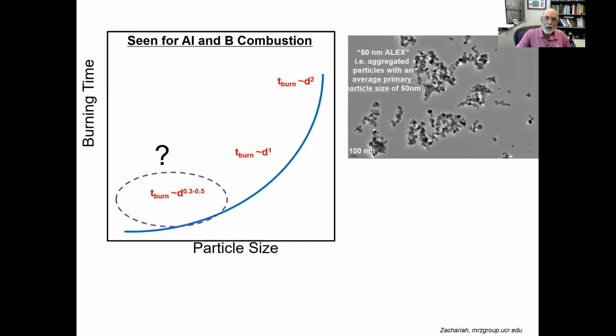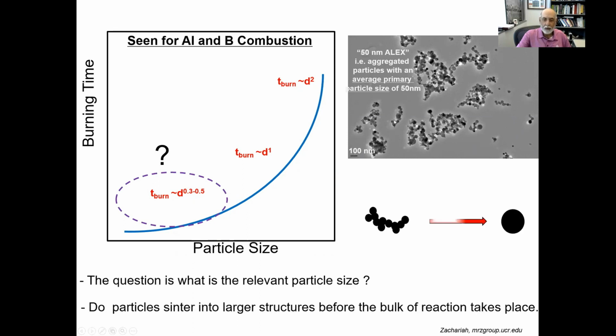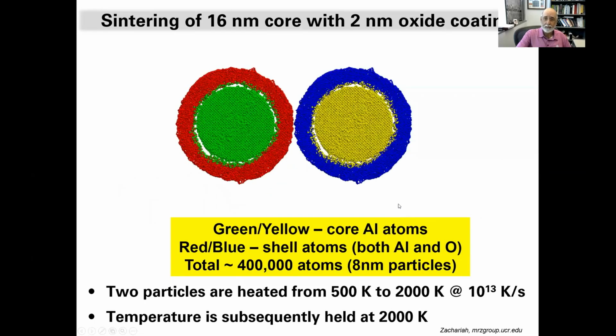And if you look at what actual nanomaterials look like, this is what they look like. And so what is this particle size? Is it the size of this aggregate, or is it the size of the little object that comprises the aggregate? In other words, the primary particle size. So what is the relevant particle size? And really the reason I ask this is because this aggregate can turn into this object on the right. And if it does, then its effective surface area is much, much lower. And so you would expect it to react a lot less.